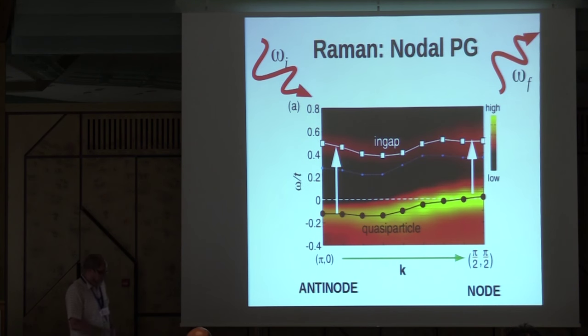So what we said is that if it's true, perhaps we can see it in some spectroscopy. Now, it's really difficult, because what we would like to show is that in the nodal point there is still a gap in the spectra, even if it is not at the Fermi level. It's shifted a bit in energy to positive value. Ideally one would like to use ARPES, but ARPES cannot assess the positive energy very easily. It's very difficult. And above all, it cannot assess such high energy. So we said, perhaps Raman will be able to do that.